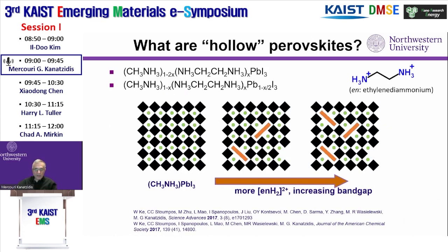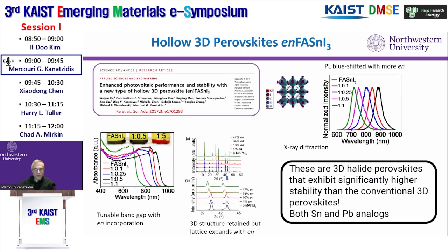These are the hollow perovskites. If you use ethylene diammonium, you don't make a 2D perovskite. You make something that is 3D, and it has the same diffraction pattern as the 3D. So it almost looks like it doesn't work. If you use ethylene diammonium in the synthesis, you get these diffraction patterns, which look just like the 3D. And you say, wow, it didn't work.